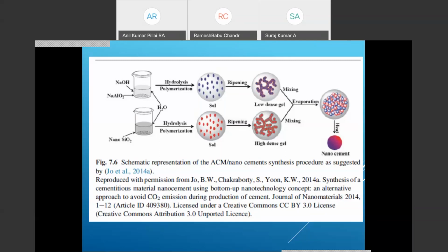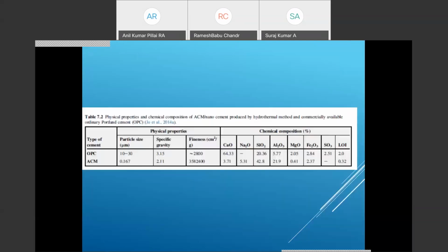They use the sol gel process. The low density gel is mixed with the high density gel, and on evaporation it yields nano cement. So here are the physical properties and chemical composition of alternate cementitious material and nano cement by hydrothermal method, and commercially available cement. See, for OPC, the particle size range is 10 to 30 micrometers, specific gravity is 3.15, fineness is 2800. But in case of alternate cementitious material, the particle size is 0.167 micrometer, specific gravity is 2.11, fineness is 3,582,400 centimeters square per gram.